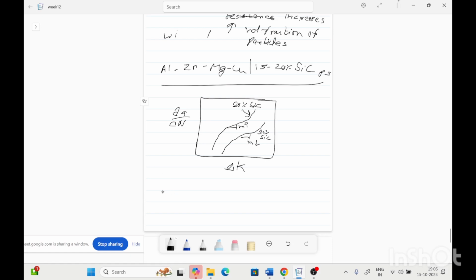And if we see the aging effect on the fatigue strength or fatigue crack growth. So aging effect generally is less. So only if we see for 30%, this curve can be drawn for the aged condition, means it can be underaged or overaged. Similarly for the 20% silicon carbide, the aged change will be very less. So this is for 7000 series alloy.